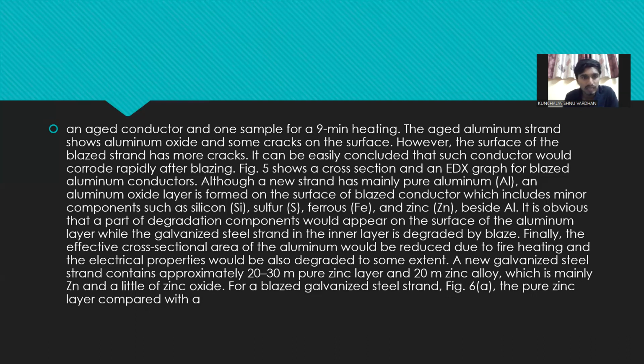The aged aluminum strand shows aluminum oxide and some cracks on the surface. However, the surface of the blazed strand has more cracks. It can be easily concluded that such conductors would corrode rapidly after blazing. Although a new strand has mainly pure aluminum, an aluminum oxide layer is formed on the surface of the blazed conductor, which includes minor components such as silicon, sulfur, iron and zinc beside Al.